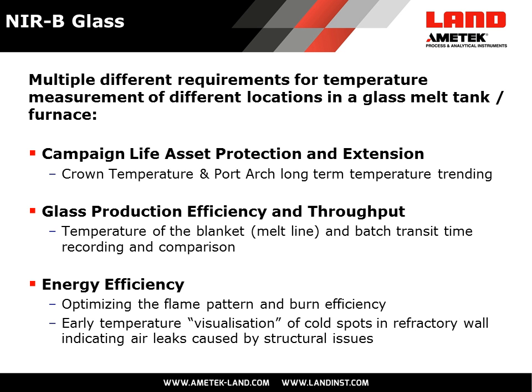The first one is that by monitoring the temperature throughout the glass tank in the radiometric thermal image, you're able to measure multiple temperature points, and within those multiple temperature areas, you're able to trend temperatures, measure important areas like the crown of the furnace, the areas at the tops of the ports, the port arches. And by doing this in a repeatable way, you're able to predict and prevent damage to the refractory materials and extend the campaign life of the glass tank.